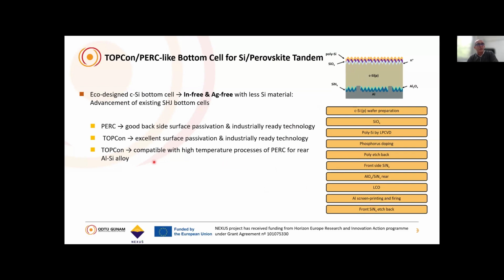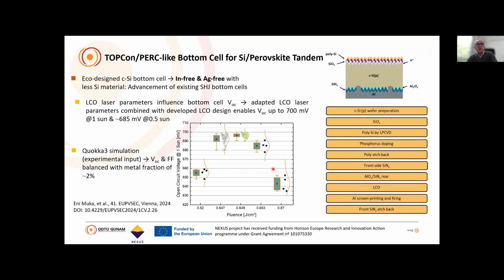Here you see the fabrication steps. I'm not going to explain all the details, but we have a well-known, well-established backside technology and good passivation as of today, because PERC cells are well known, and this structure is very compatible with high temperature processes and also with industrial production. In this structure, we have measured the open circuit voltage at one sun. We have obtained VOC values up to 700 millivolt. Of course, it gives us an indium-free and silver-free structure for the tandem fabrication.